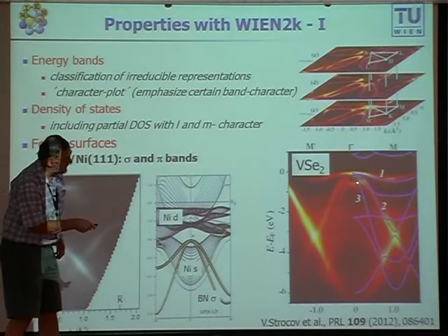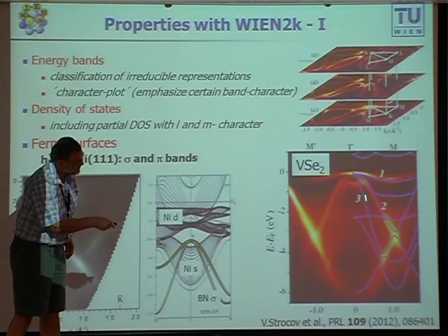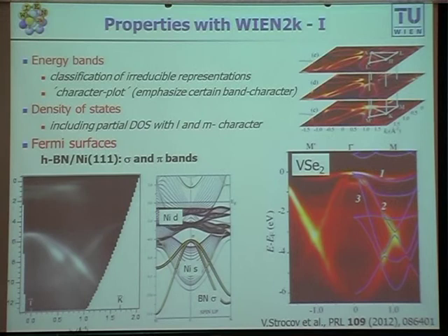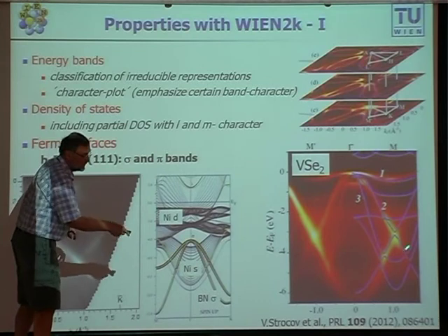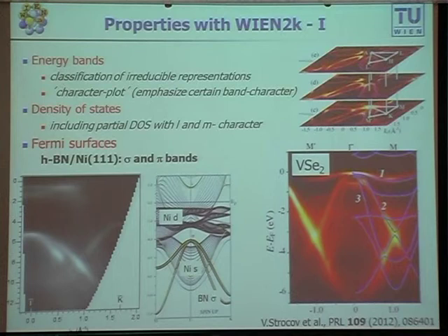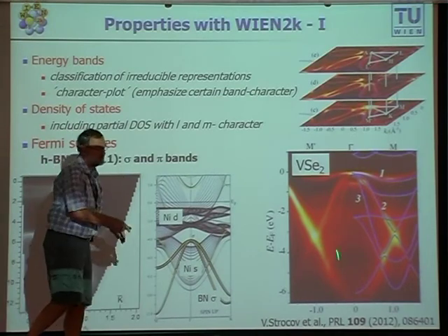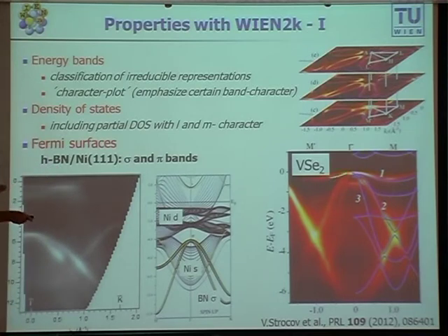And you can compare now the band dispersion with the calculations, and you find, I would say, a pretty good agreement between theory and experiment, even though these bands, these eigenvalues, have strictly speaking no meaning. So you would have to do formally, for instance, a GW calculation, doing these quasi-particle energies, and then you could justify comparing theoretically the bands with the experiment. In practice, in a material like this, it works perfectly, pretty good, let's say.